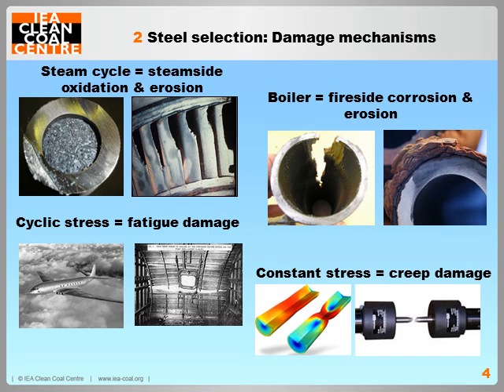Both of these chemical attack mechanisms slowly degrade the materials. There's also constant stress, which is caused by high pressures and high physical loads. This results in cracks on the inside of the material, and this is known as creep damage. There's also cyclic stresses, which is induced by fluctuating temperatures and pressures. This results in cracks on the outside of materials, and this is called fatigue damage.